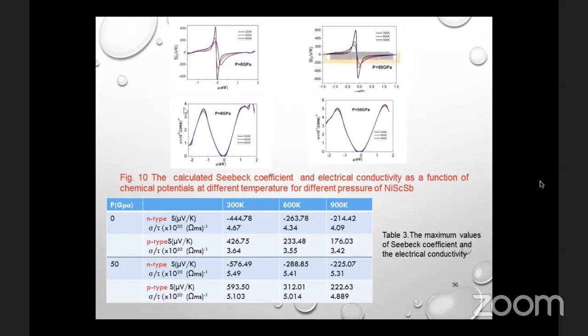The other property, electrical conductivity divided by relaxation time, is another important factor that influences the thermoelectric figure of merit. In the given figure 10 also, we found that there is no significant change in this parameter with temperature, but it is found to increase with increase in concentration and pressure. We see that the N-type region has high electrical conductivity compared to the P-type region. Note that increasing temperature has no important variation on electrical conductivity for this compound, but with increasing pressure, electrical conductivity increases.